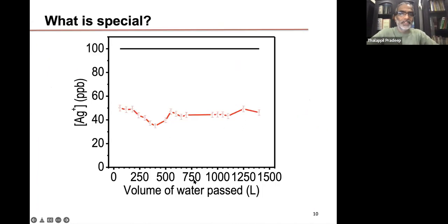Now, why are we creating such materials? In this particular specific case, the particles are silver nanoparticles. They release silver ions in water at a definite concentration. And this concentration does not go down. Normally, if you create silver nanoparticles, they do produce silver ions. But these silver ions concentration go down in real water, especially water containing all the contaminants, the concentration goes down in about a few days. As a result, there is no antibacterial activity this material can have, and this activity comes down.